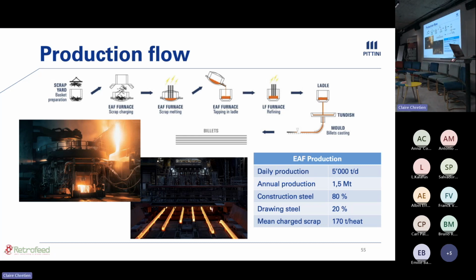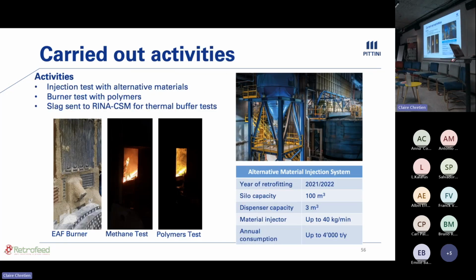We have an electric arc furnace in order to produce carbon steel. And we have, of course, other steps, which are ladle refining and the continuous casting machine, as you can see in the image below, with 6 lines. We produce almost 5,000 tons of liquid steel per day, with an annual production of 1.5 million tons of steel. And we produce almost 80% construction steel and 20% drawing steel. The main charge is steel scrap, 170 tons per heat, and we produce 150 tons per heat of liquid steel.